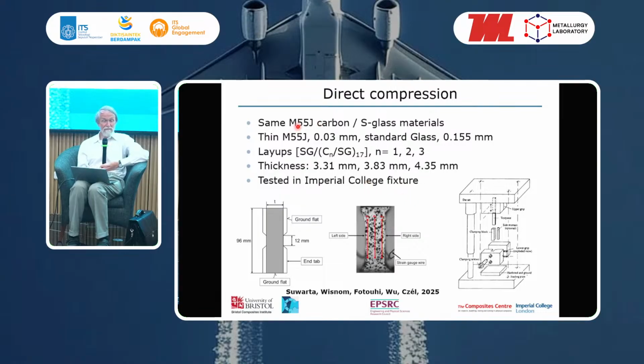The same M55J carbon fiber and S-glass, with 2 layers of M55, or different numbers of M55 plies between the glass, and multiple layers through the thickness, so 17 repeats of this sublaminate, because we need quite a thick specimen to load it in compression. The number of carbon plies together was varied between 1, 2, and 3. So these specimens are between 3 or 4 millimeters thick.